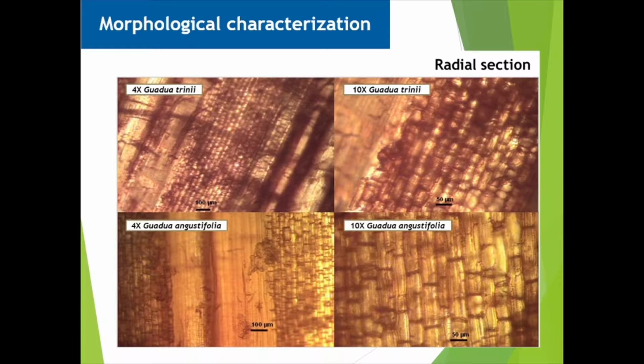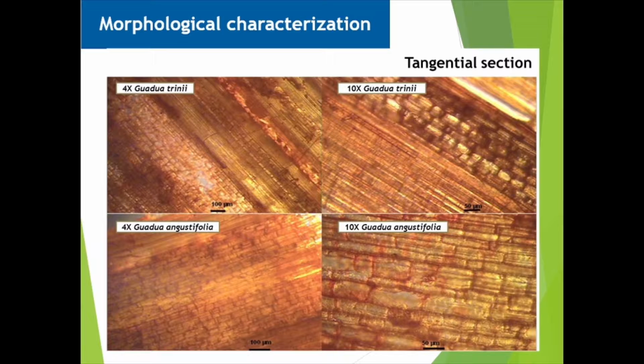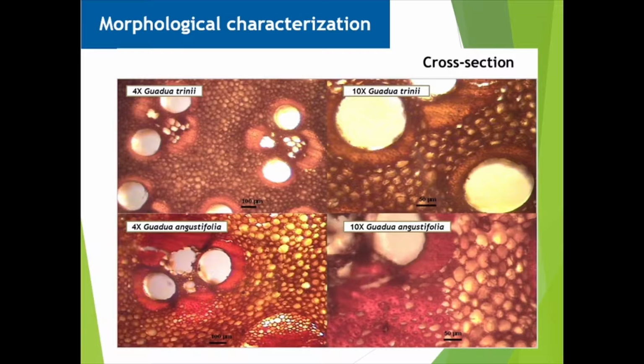The analysis of the histological section of the small pieces of the stem was carried out from the thin lamina using a microtome. We observed the radial section of each species, measured in lenses of 4 and 10x of the microscope. We can see the vascular bundles and rays. In the same previous lenses, the images of the longitudinal section for each species can now be observed. We observe vessels, fibers, and cambium. Finally, in the cross-section, we can see vascular bundles, parenchyma, fibers, and cambium.